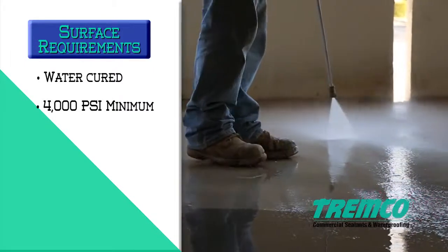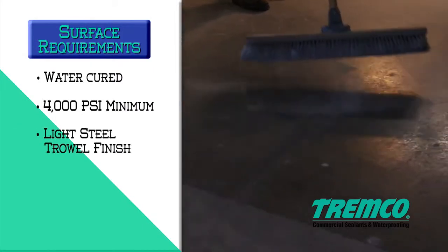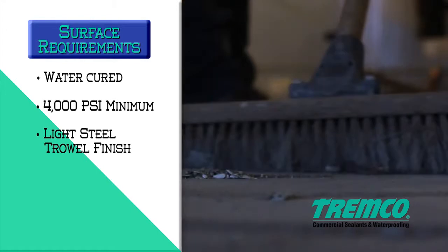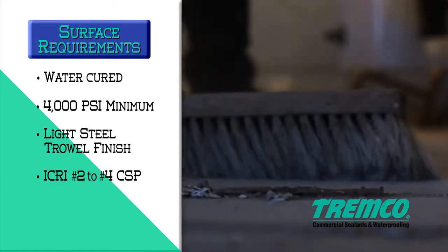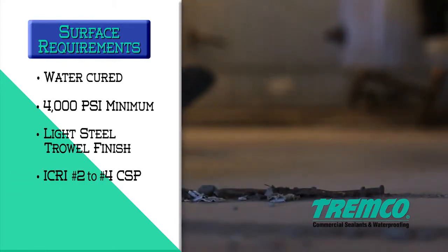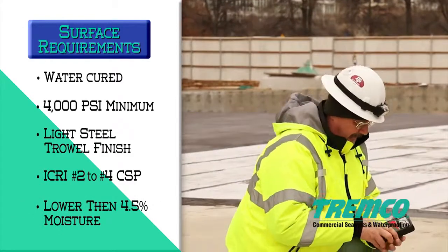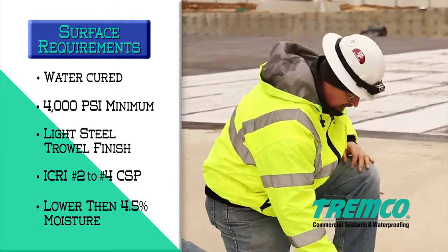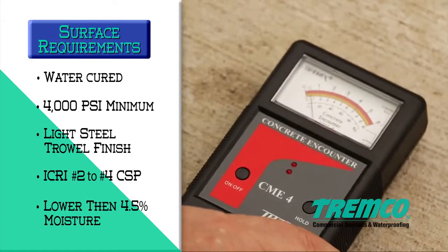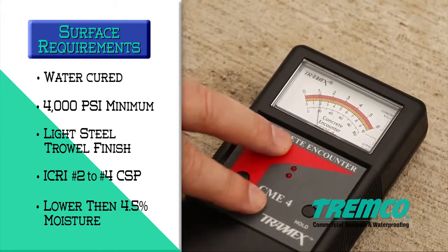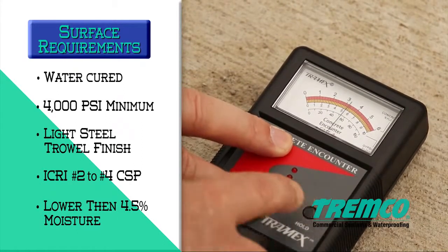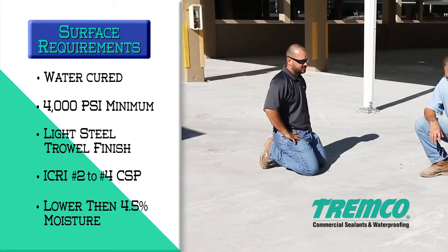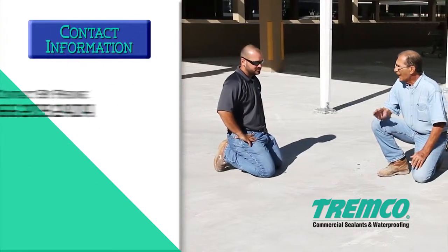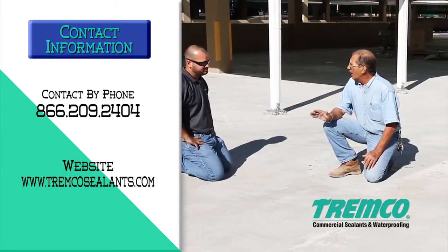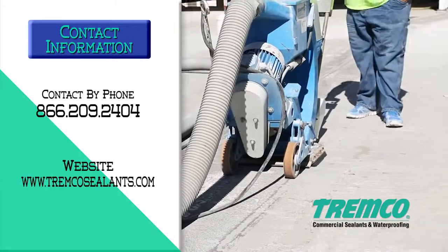The concrete finish shall be a light steel trowel followed by a fine hair broom or equivalent ICRI number 2 to number 4 CSP. Moisture content in the concrete must be lower than 4.5% as measured using a Tremco CME4 moisture meter. Depending on concrete construction and job site location, additional concrete testing may be required. Please contact your local Tremco sales or technical representative for more information.